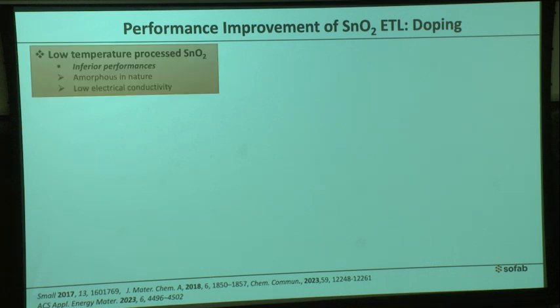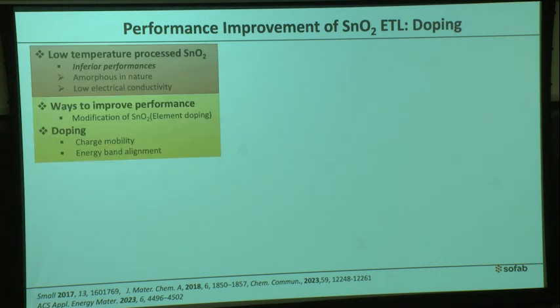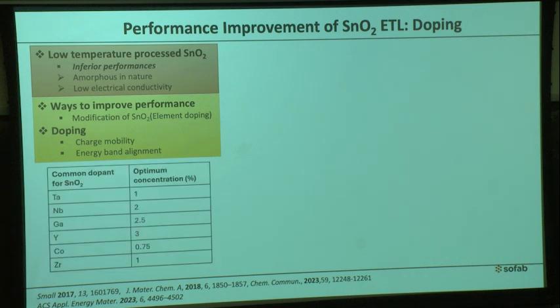The tin oxide we use here is low temperature processed, and to make metal oxide efficient, we need to heat it to high temperature. However, we can improve the performance of low temperature processed tin oxide using different modifications. The first approach people use is elemental doping, and here we also use the same strategy.